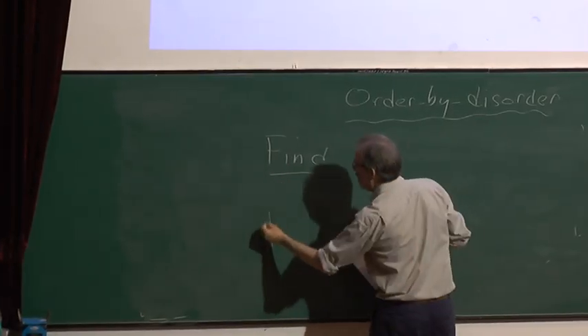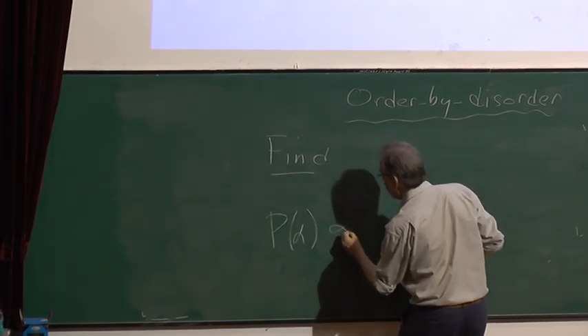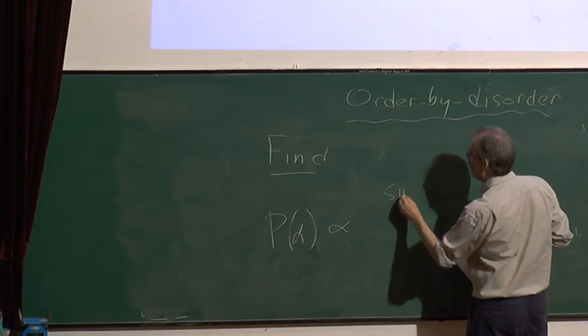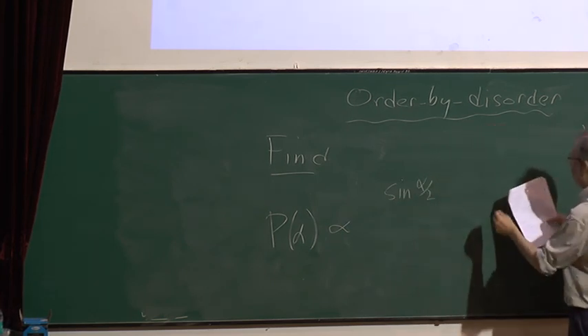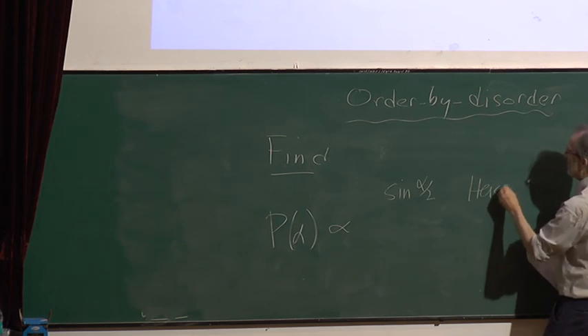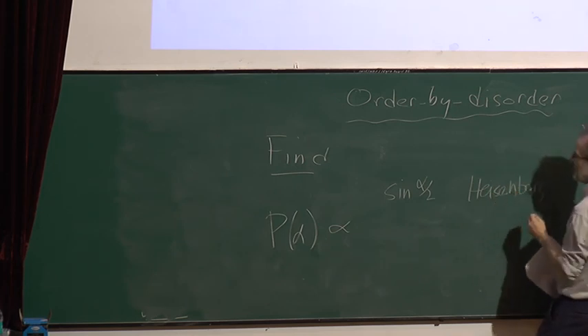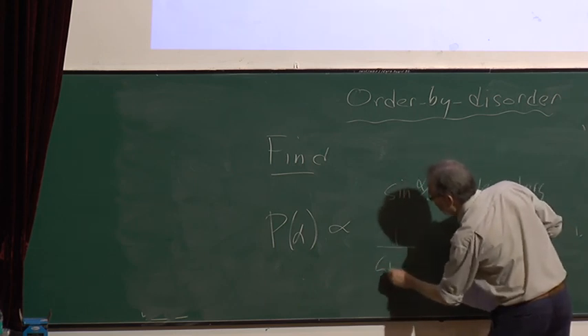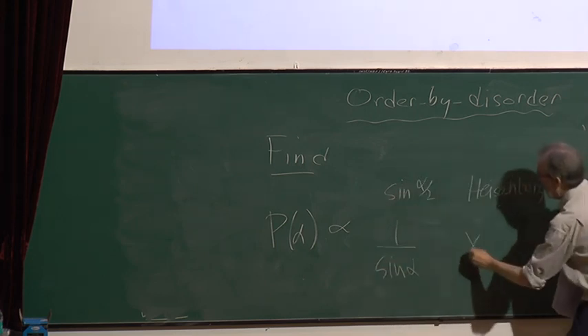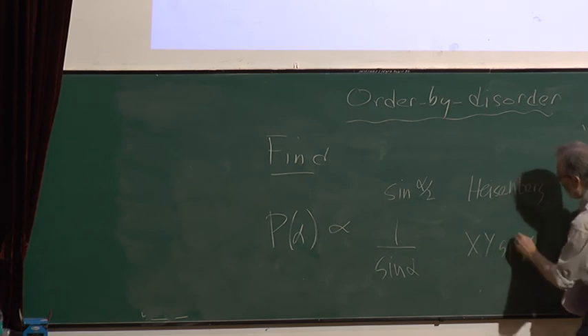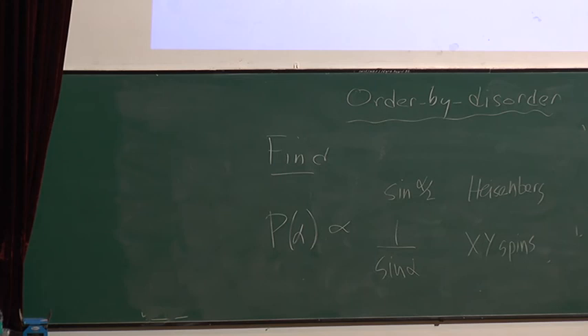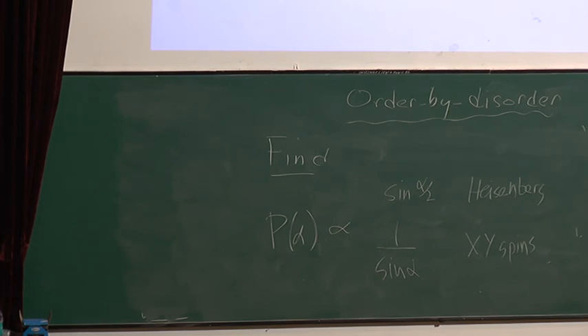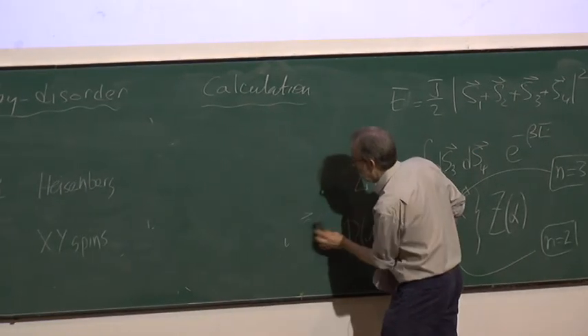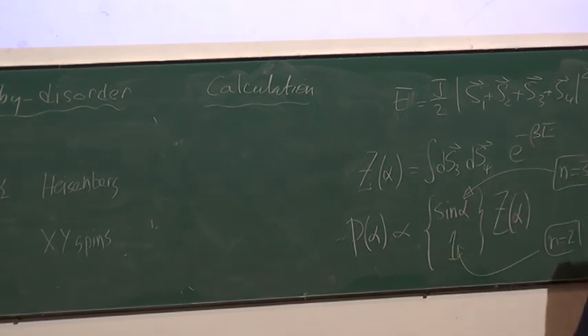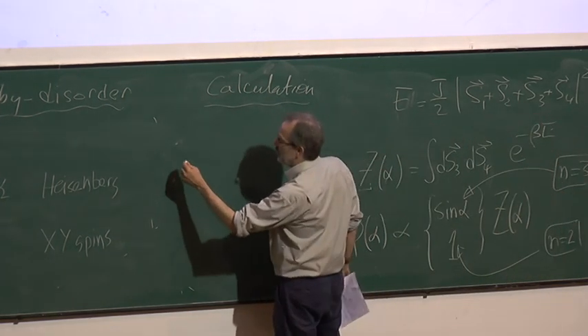You find that P of alpha is proportional to sine alpha over 2 for Heisenberg, and 1 over sine alpha for xy spins. What that means physically is that in the Heisenberg cluster, all orientations, all configurations of spins in the ground state are possible at low temperature.